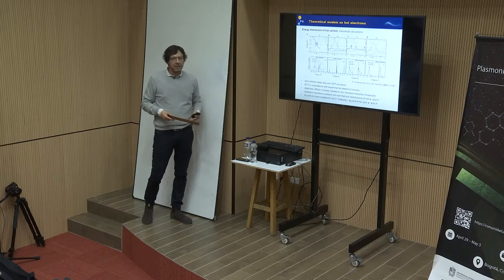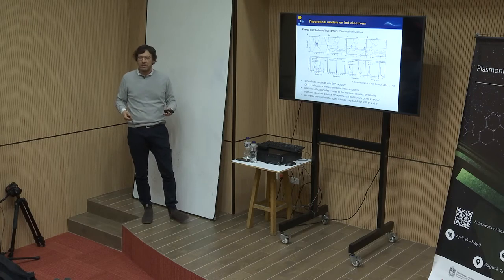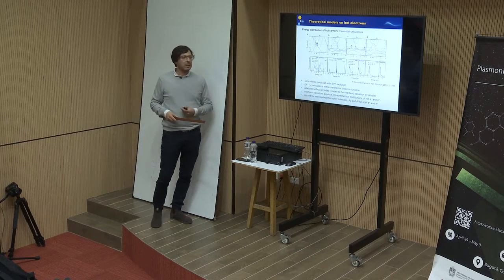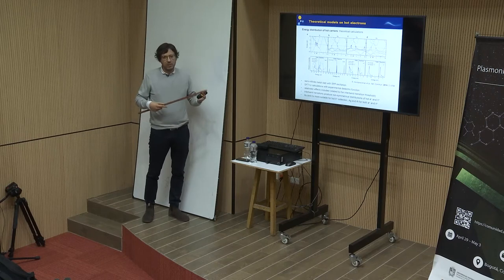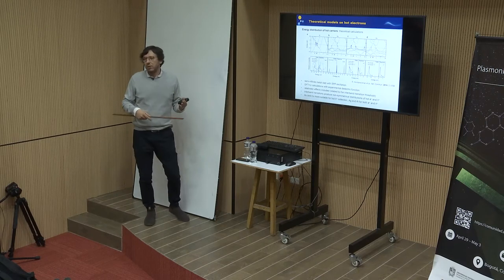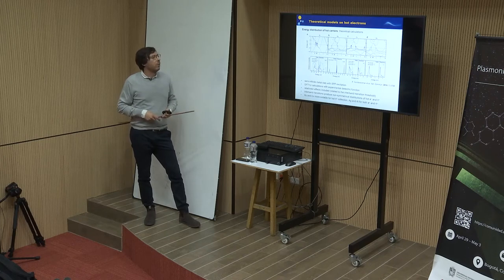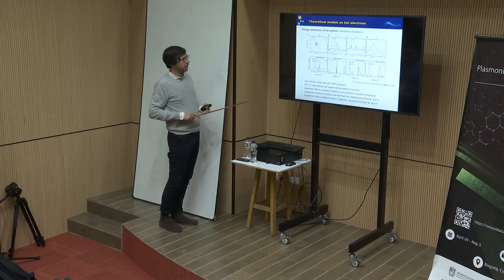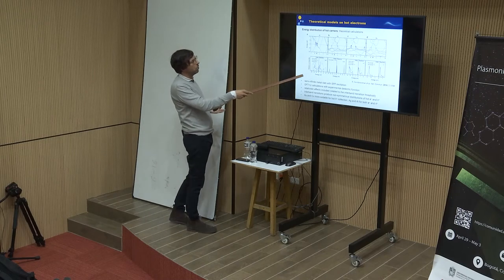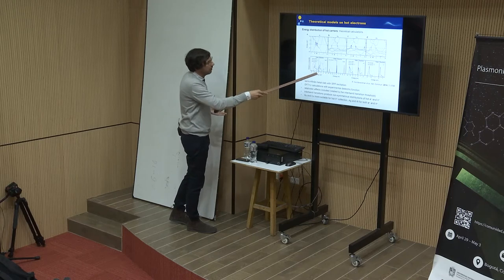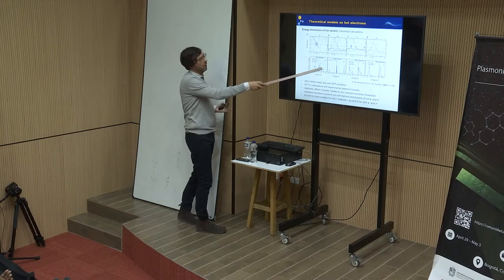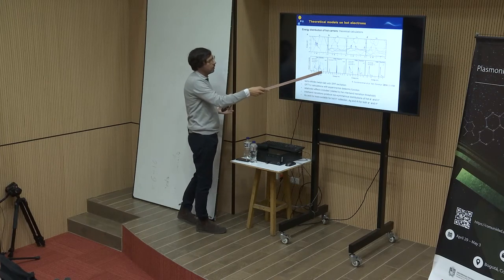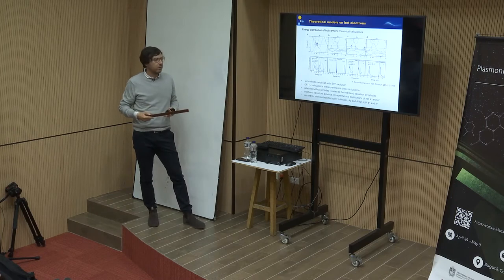So, depending on the density of states of the metals, we can create different energy distributions. My opinion is that, of course, because this process is a many-body interaction, it depends on the occupation of the density of states of the materials. As we can see here, aluminum and silver have a quite symmetric distribution of carriers, so electrons and holes have similar energy distribution and amount generated.